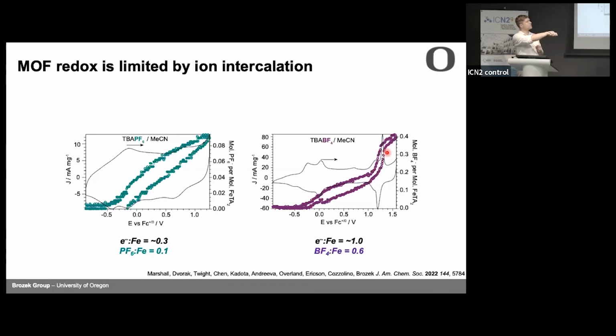And it turns out that when you see really sharp CVs like this, is how people think about phase changes, or how people think about solvent reorganization and intercalation chemistry. And so this is really consistent with this idea that out here, you're oxidizing iron sites, you're barely doing any intercalation. But the way that you get this oxidation to happen on the inside of the nanocrystal is you provide all of this overpotential, and then all of a sudden, the BF4 anions, they desolvate, they intercalate, they go into the nanocrystal, and now you can oxidize the iron sites.